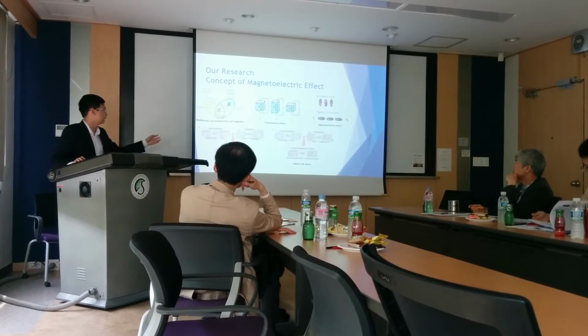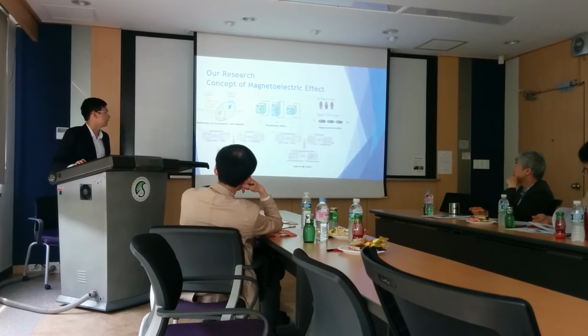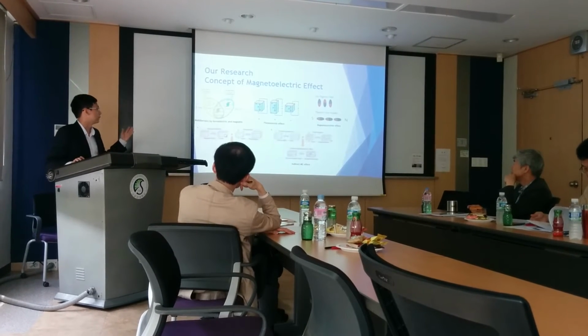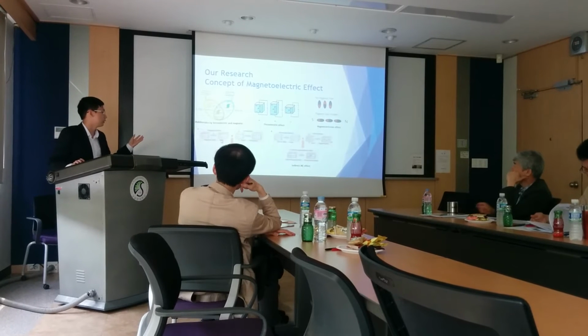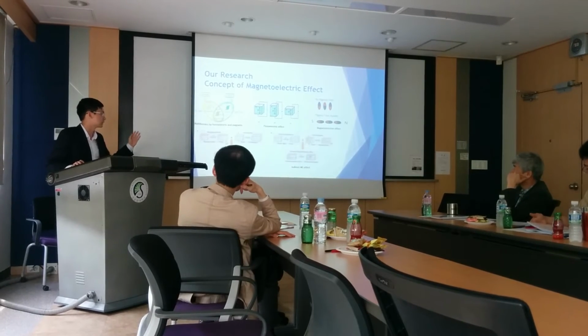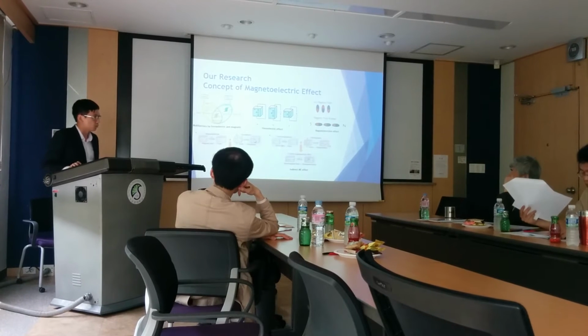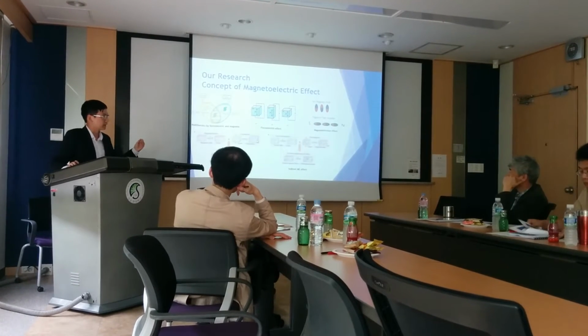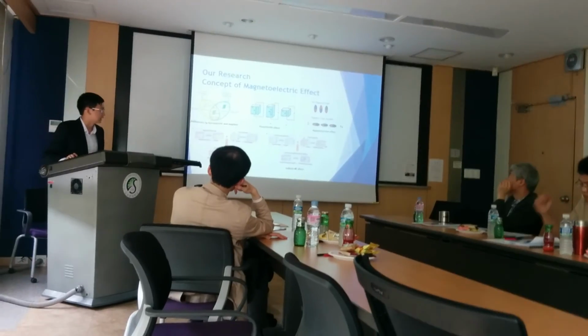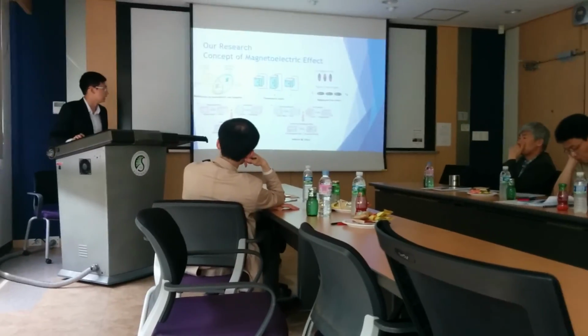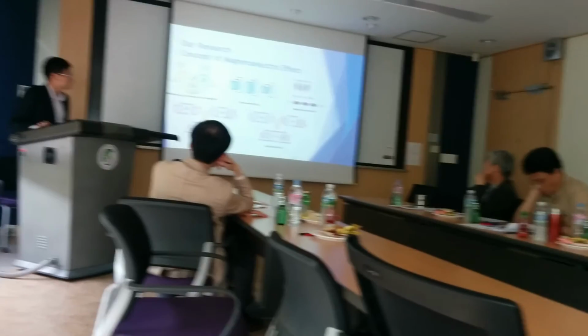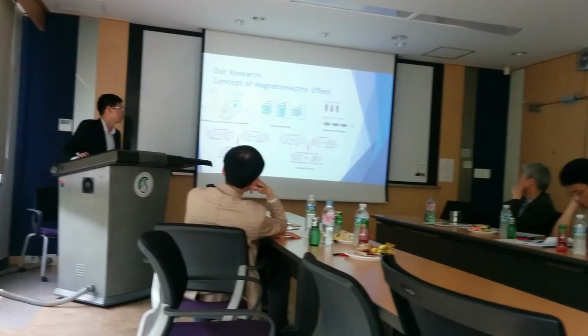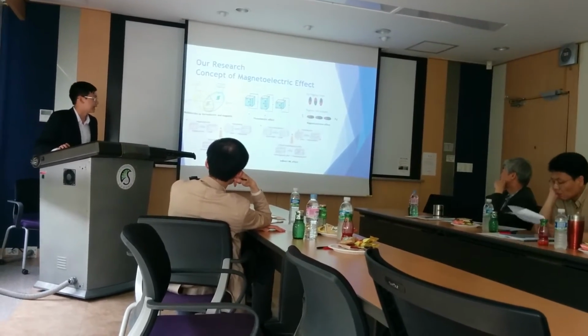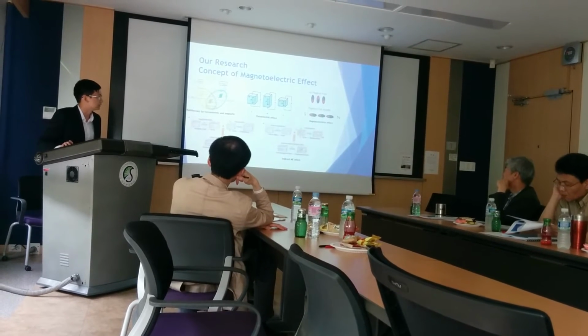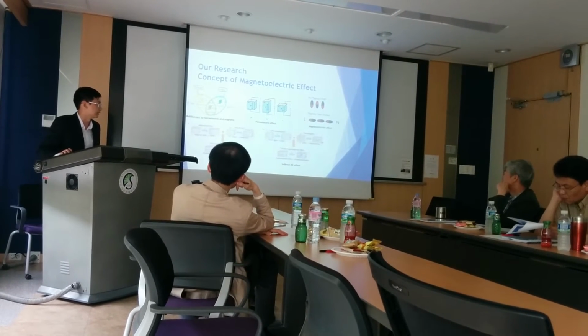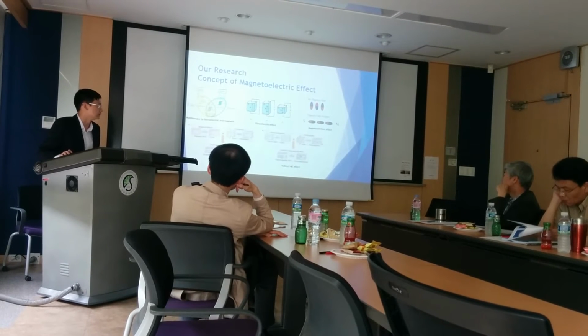There are 2 kinds of ME effect in the ME composite: the direct ME effect and the indirect ME effect. In the direct ME effect, when we apply the magnetic field to the ME composite, the magnetostrictive material will change shape and transmit the strain to the piezoelectric phase. When the piezoelectric phase gets the strain, it will make charge at the two phases and make polarization in the ME composite. In contrast, in the indirect ME effect, when we apply the electric field, the piezoelectric material will get the strain and make polarization and induce magnetization in the ME composite.